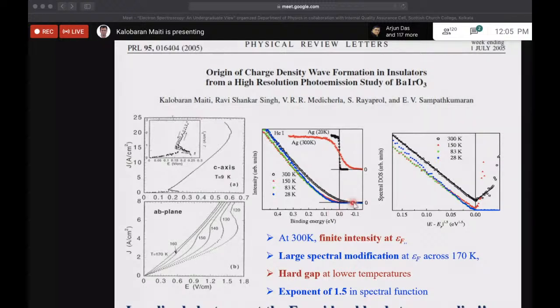So here what is happening is that this is a special kind of insulator where you have electrons at the Fermi level, which were supposed to move, but somehow they are localized. And this scenario can give you a charge density wave kind of thing, because you have electrons at the Fermi level, and that can give you a density wave. So this is one kind of puzzle that you can solve.